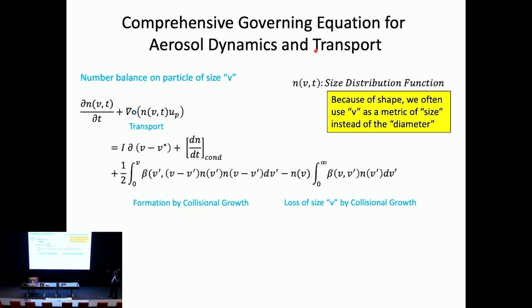But here I'll just say that n is a function of the particle size, in this case volume, and time, right? So the change in the size distribution function, there is a transport term, that's the first term. I'll tell you what that velocity term is, an expression for that. And on the right-hand side, a nucleation term. There is a critical size at which these clusters will form. Below that critical size, they just break apart, and I don't form stable clusters. So that's the delta function, and then a nucleation rate, then a condensation rate, and a collision rate, which is an integral sort of equation, right? It is a summation of everything colliding with every possible size, resulting in growth. And when you also have a negative term because you lose a certain size of particles by collision with other particles and so forth.